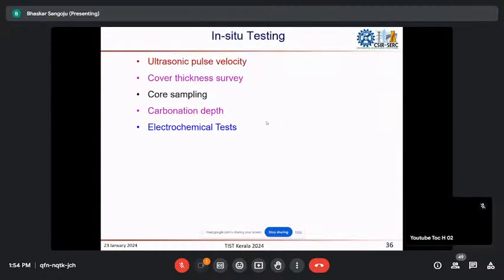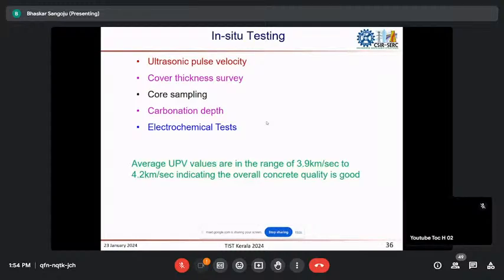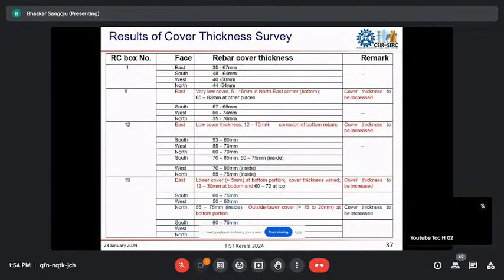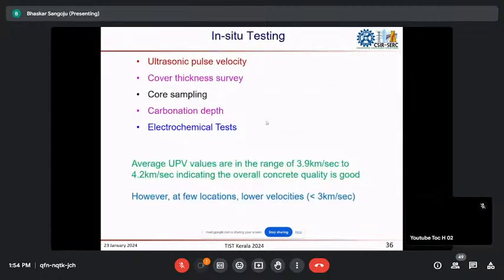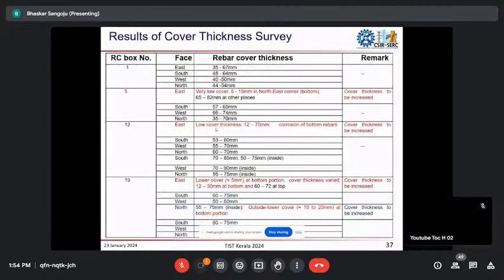We also did non-destructive testing: ultrasonic pulse velocity, cover thickness survey, core sampling, and carbonation depth, and we found the concrete strength is passing as per the design drawings. The ultrasonic pulse velocity values are good in most places, but at a few places the velocities are very low.